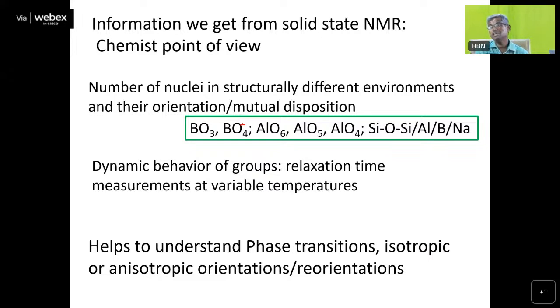I explain borosilicate and aluminosilicate because boron, aluminium, etc. have quite low atomic numbers. Once the atomic number is low, it is difficult to get good quality diffraction patterns. As you may know, the diffraction pattern depends upon the number of electrons present in the atom, Z being the atomic number of the element. If the atomic number is low, like boron, carbon, nitrogen, particularly nitrides, it is very difficult to get good diffraction information because of the low Z values. In such cases NMR wins, because NMR is highly sensitive to nuclei like boron, aluminium, etc.